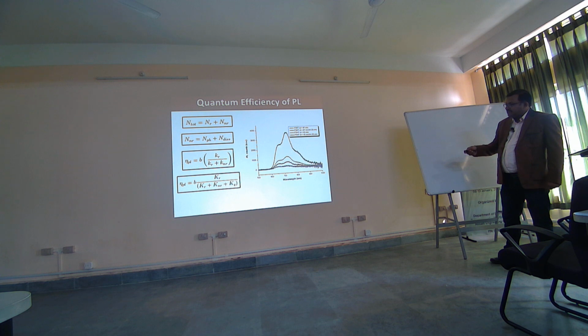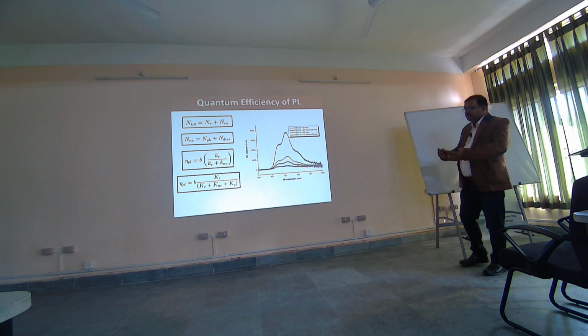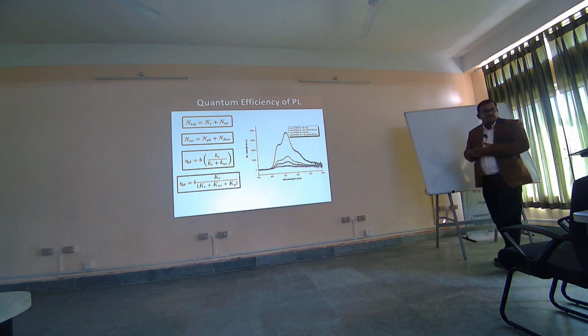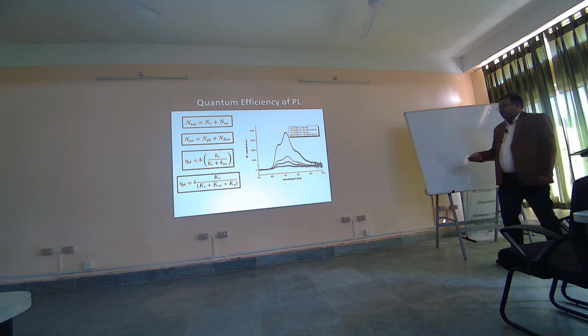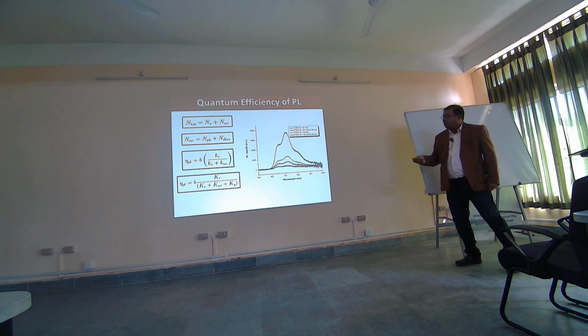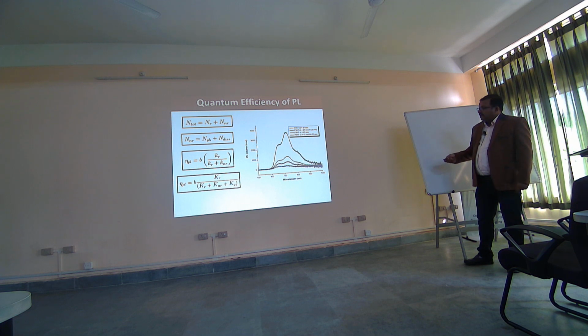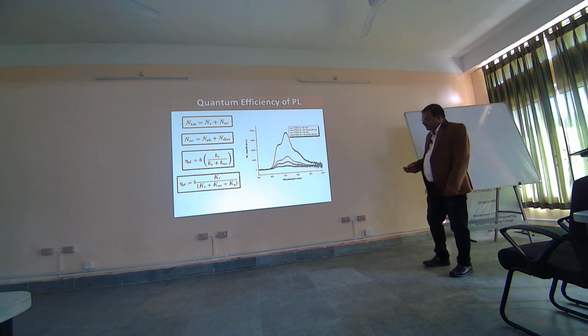If you can see these shoulder peaks and the main peak, the features are all retained, but the intensity gets decreased, from the black to the red curve, just by coating aluminum. What is happening here is that the aluminum forms some kind of Schottky junction at the interface, which leads to strong decay of excitons at the interface, and therefore a lot of excitons undergo non-radiative recombination. So an increase in non-radiative recombination may lead to a decrease in the overall PL counts. As you can see, these are the PL counts. That results in what we call PL quenching.